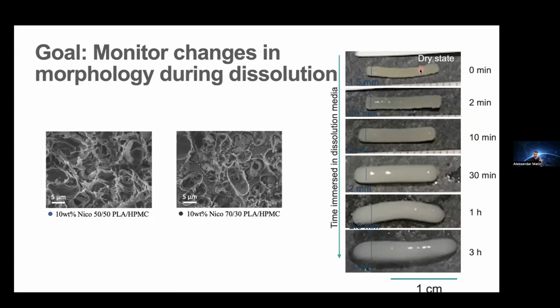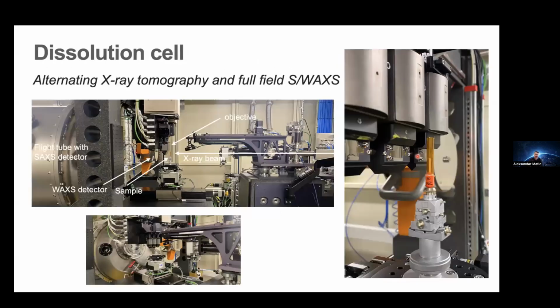And then when you put them in buffer, you can see with time, these are samples taken after different amounts of time, how the whole structure swells by the penetration of the buffer into especially the HPMC phase. And now the idea was to follow what goes on. Can we do this with X-rays? So we had here our setup. The sample is down here, X-ray beam coming in from the right. The objectives are just above. And here, if you remove the microscope, you can then do SAXS. You have the flight tube for SAXS, and you have also the wide-angle X-ray scattering detector.